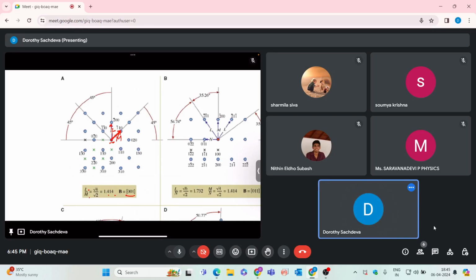As you can see, your M is having bar 1, 1, 0 plane, and so the distance will be under root of 1 square plus bar 1 square plus 0 square, that will be under root 2, and for L your distance will be bar 2 square plus 0 square plus 0 square, that will be under root 4. So the ratio of L to M will be under root 2, so if you just find out the ratio between the non-collinear planes in your diffraction pattern, then also you can find out the zone axis.